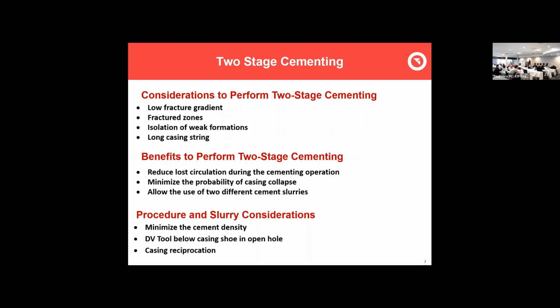Here I do have listed the use of 2 different cement slurries. For the most part, we try and cement with as low a density as we can that still has good compressive strength, but we're looking at, like most typical jobs, anywhere from 13.5 to 15.5 pounds is what we use.